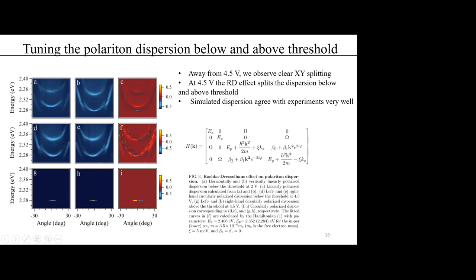Beta 0 denotes the X-Y splitting, and beta 1 represents the TE-TM splitting. Phi is the polar angle with the range from 0 to pi. So we can see that the theoretical curves agree with the experimental dispersion very well.